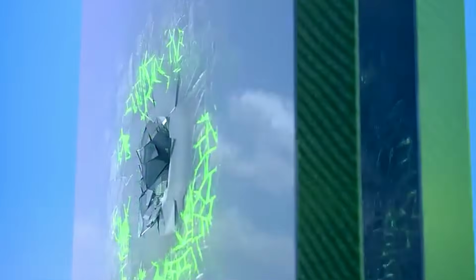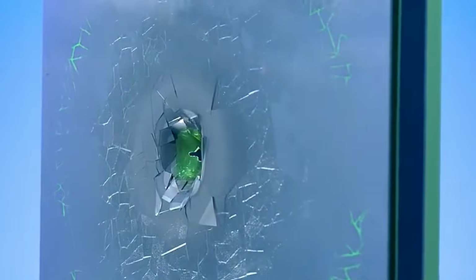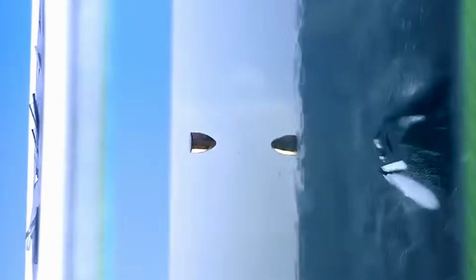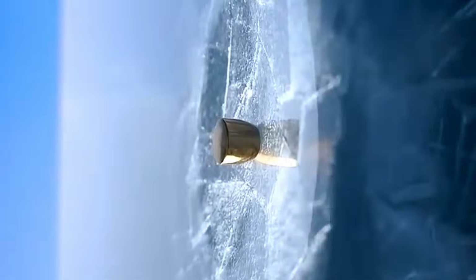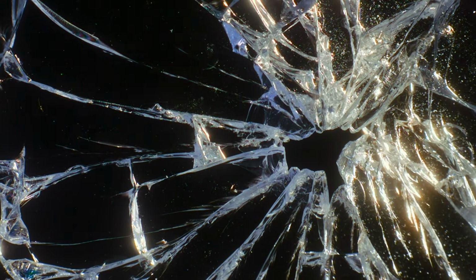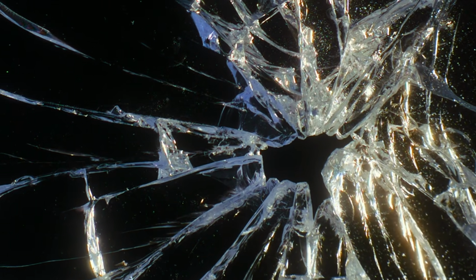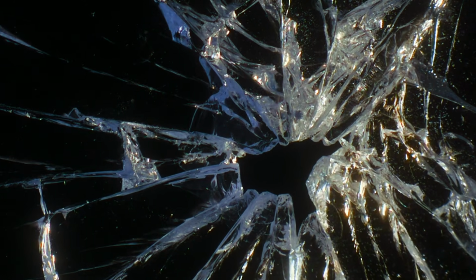Rather than resisting impact through hardness alone, the glass survives through flexibility, redirecting violent energy across its laminated structure to prevent deadly penetration. After every test, technicians inspect the shattered glass under microscopes, studying crack formations and penetration depth. Even a tiny fragment breaking through is a complete failure. Bulletproof glass must stop every round without shedding dangerous splinters.